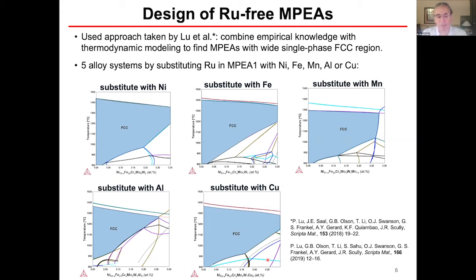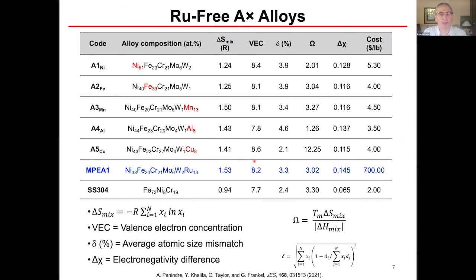And in fact, a major thrust in this work is to try and strengthen these materials by first solutionizing and then heat treating in a region where we would expect to precipitate these other phases that could be hardening. And I'm not going to talk about that work, but indeed we can form very interesting phases, very interesting microstructures by that route of solutionizing and then heat treating at lower temperatures. And Nick talked a little bit about the ability to have multi-phase structures that are corrosion resistant, but actually what we find is more or less what is expected, that these types of multi-phase structures lead to a degradation in the corrosion performance. Again, I'm not going to talk about it, but that is where the focus is.